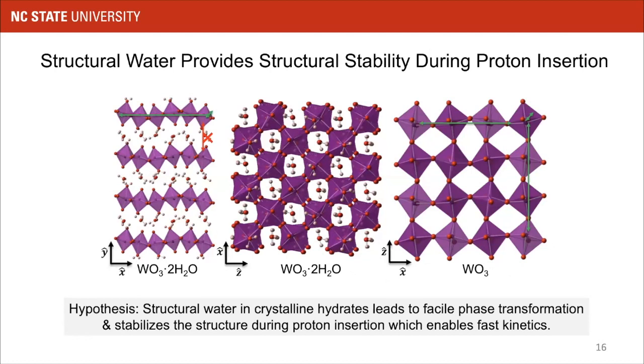So this led us to a revised hypothesis for what's happening with these crystalline tungsten oxide hydrates. We don't see evidence of protons transporting along these water networks. They're more likely associated with the bridging oxygens within each of these layers. We do see evidence of structural transitions associated with changes in the tungsten-oxygen bond distances within this layer. So this is a top-down view on these layers. And so that makes our hypothesis more that the structural water is providing structural stability during proton insertion.